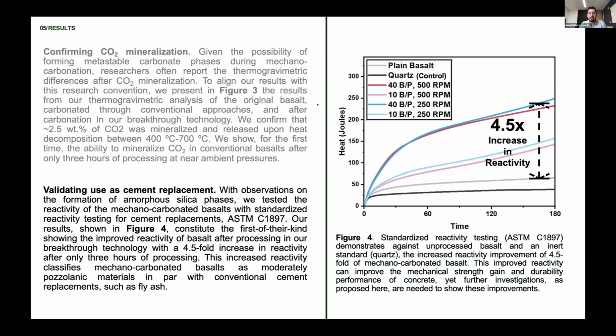And this is one of the most exciting results that we have: not only can we carbonate these materials and sequester some CO2, but in that process we can also improve the reactivity such that we can create domestic cement replacements. So this is really exciting. Now, the light blue and light pink curves here are for ball to powder ratios of 10, and you can see that reactivity is much lower, but you see an increase in reactivity nonetheless. So again, this shows that our technologies can be modified and improved upon.